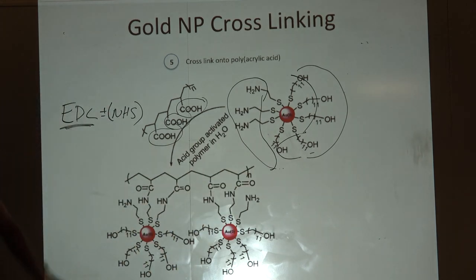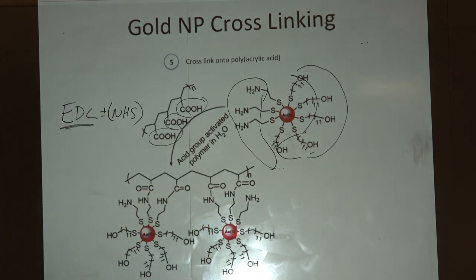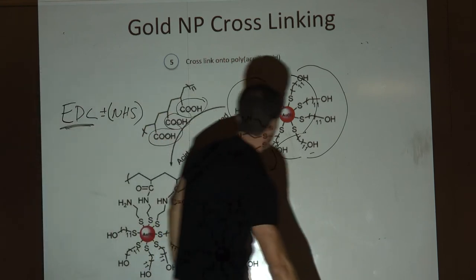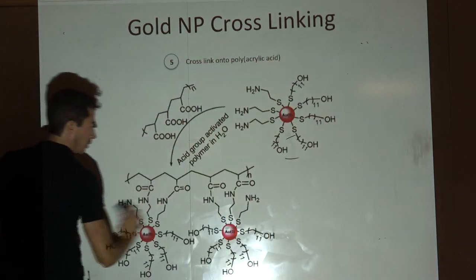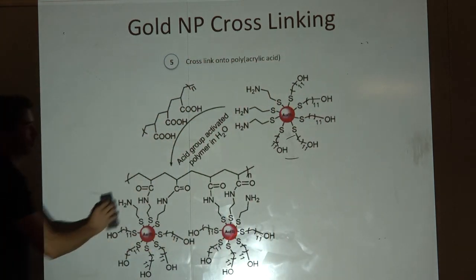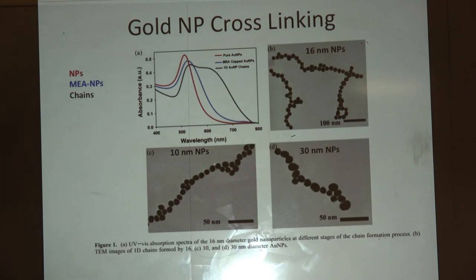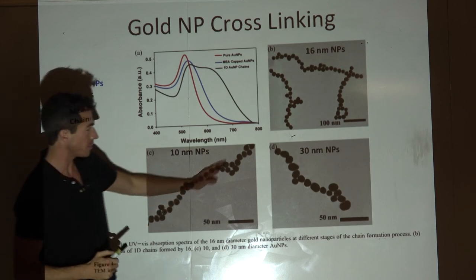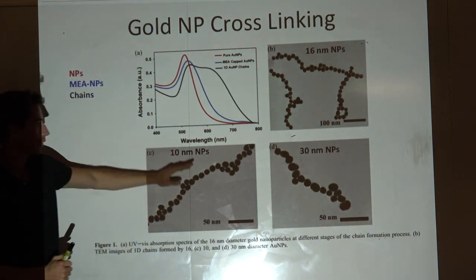We have this particle that is half hydroxyls and half amines. Then we add this to a group with carboxylic acid, our polymer of interest. What would we use to link a primary amine to a carboxylic acid? EDC, and we could have NHS to accelerate. We could dump that in and cross-link these to make peptide bonds. We're decorating the polymer backbone with nanoparticles.